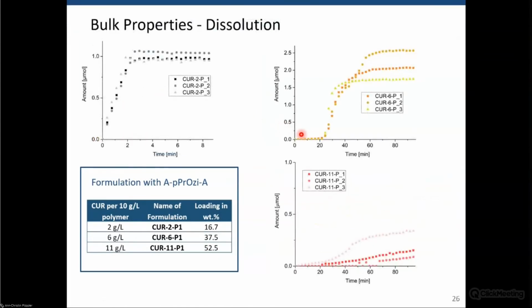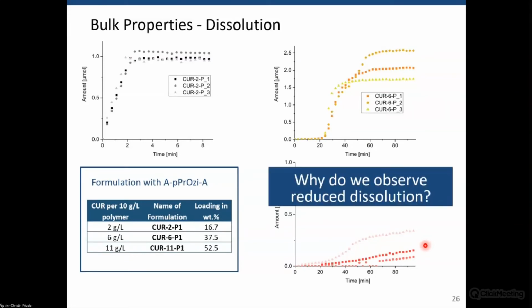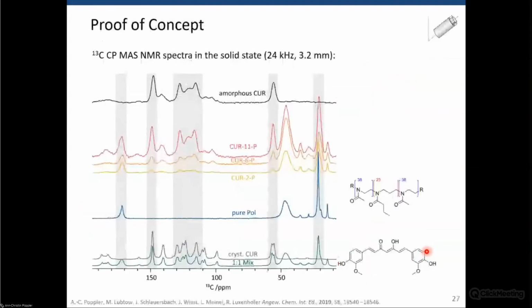And we also check properties, because we are now in the section of structure property relations, and you can see that the dissolution is good for the low loading, it's okay-ish for the medium loading, and it's really poor for the high loading. So we have to compromise the dissolution, and again the question is why? Do we find something on the molecular level to explain this?